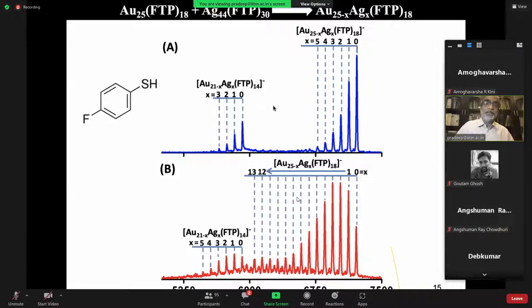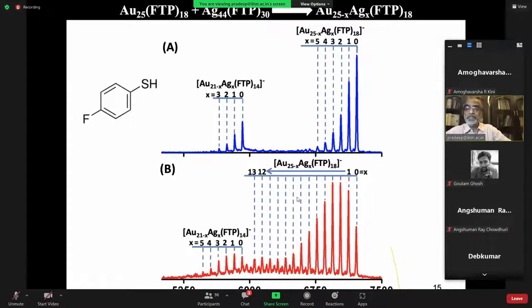So we measured the mass spectrum of this cluster and this cluster mixed together in solution. At that point in time, this was a MALDI spectrum, matrix-assisted laser desorption ionization mass spectrum. And if you measure the mass spectrum of just this cluster, you get one peak and another peak. This peak is gold 25, FTP is this thiol, 18, 1 minus. And this peak is Au4 FTP4 loss from this, giving you Au21 FTP14 minus.